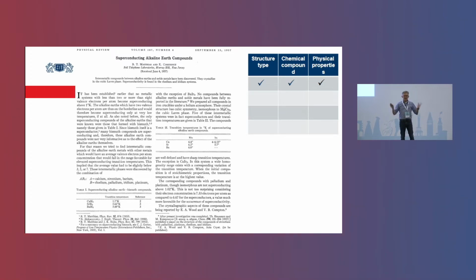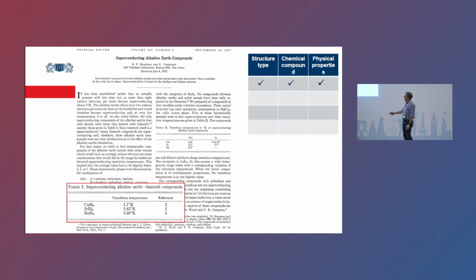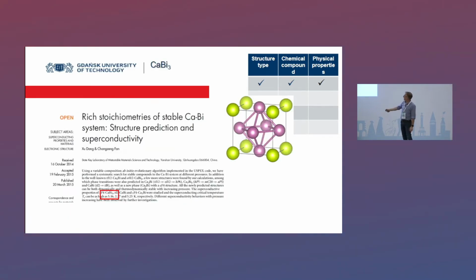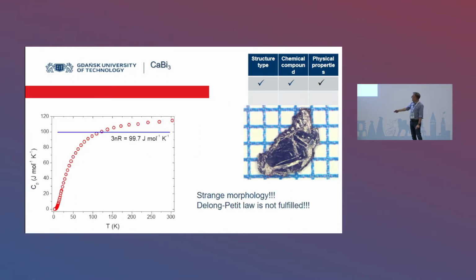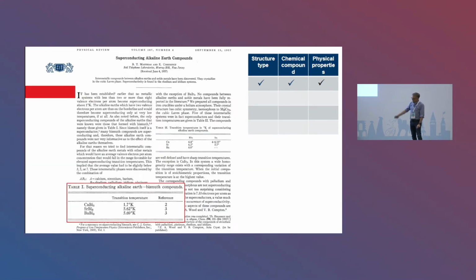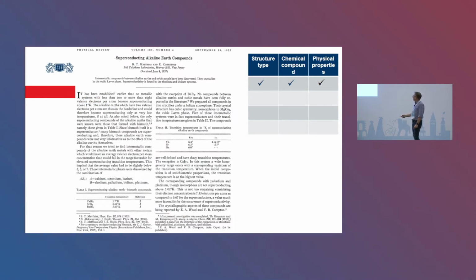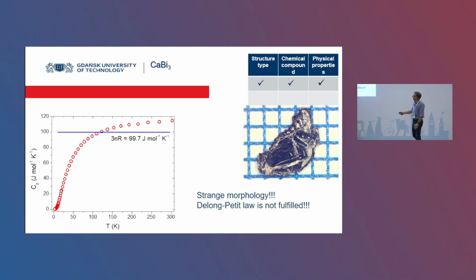Everything is known, but we were interested just because there were no superconducting properties for calcium bismuth 2. And besides, Tc seems to be strange, 1.7 Kelvin. And another thing is that there was a theory paper published in Scientific Reports, and theorists expected Tc as high as 5.16. So it's way higher than 1.7 in Bernd Matthias' paper. And my student who is sitting here, now he's not my student, he's already a PhD and DSc candidate, grew crystals. And as you can see, calcium bismuth 3 looks like that.